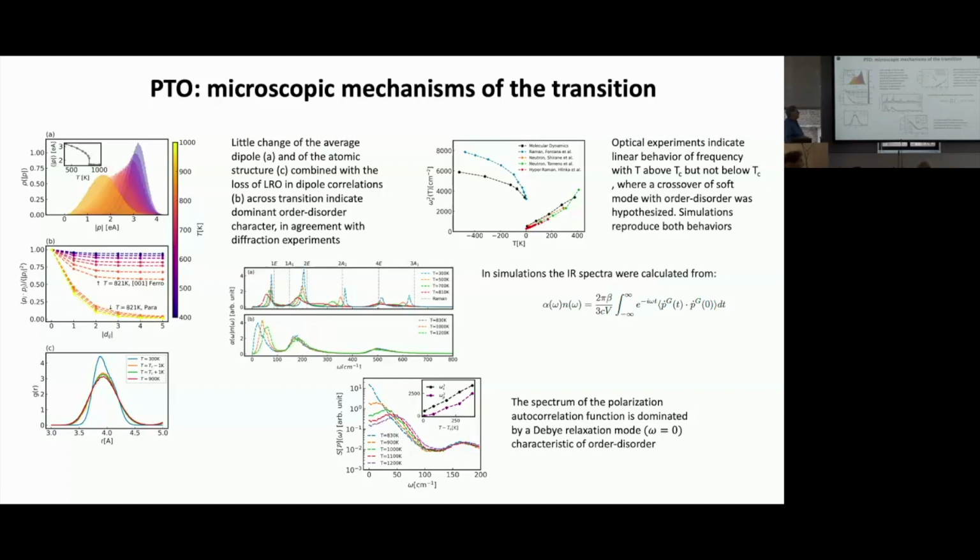And now, can we understand this behavior in the optical spectra? Well, we didn't compute the Raman spectra. The Raman spectra will involve studying the autocorrelation of the polarizability, which we can do, and we have done in some cases, but not here. Here we look only at the infrared spectra, which is related to this time autocorrelation function.